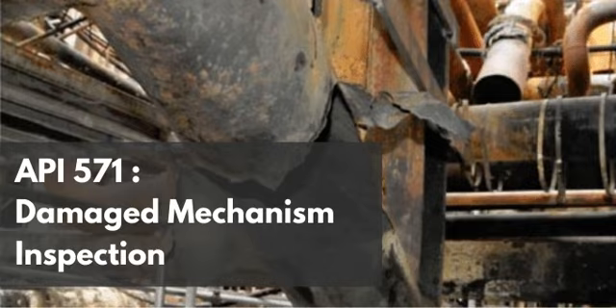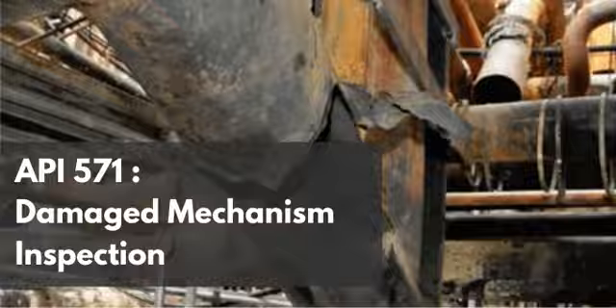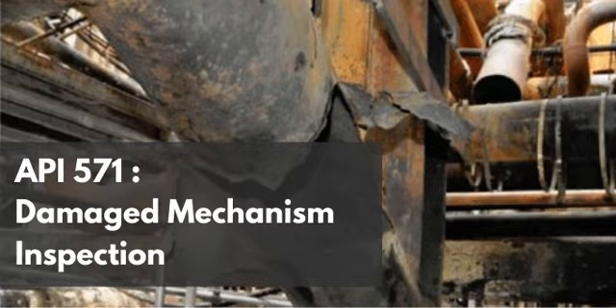This rarely results in a single straight fissure. Instead, it bifurcates. Yeah, it splits off into multiple directions following the chaotic topography of the grain boundaries. I imagine under a metallographic microscope, it looks almost like a dendritic structure, like the root system of a tree. Or a microscopic lightning strike permanently etched right into the steel. So if a metallurgist sees an intergranular branching oxide-filled fissure sitting a tenth of an inch from a weld toe, the diagnosis is confirmed. Amine SCC.